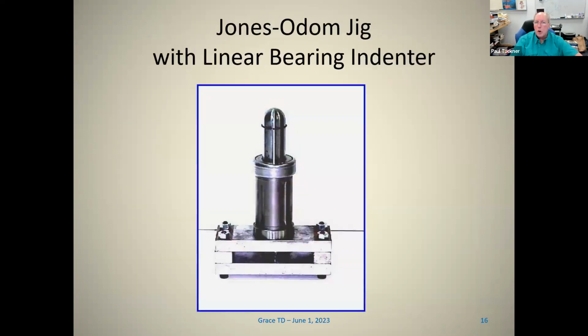This is a Jones-Odom jig, which was a really good design. What they use is a linear bearing indenter, and that was to ensure that the specimens were loaded in parallel faces, actually down the center of the specimen. But the problem with this is that it used large compression set buttons and the jigs are very large.